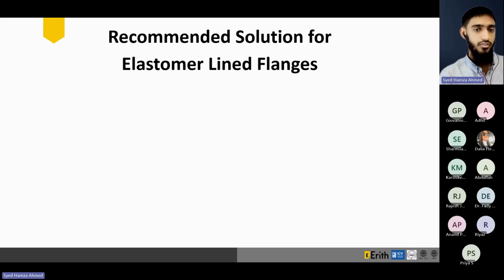Talking about elastomer lined flanges, we believe the best solution to this challenge is a thinner gasket, like a 1/32 inch or a 1/64 inch gasket made out of Gylon style 3522. The style 3522 material has very good permeation resistance, and when it is kept thin, it minimizes the amount of outward force that can be generated at the inner edges by the system pressure. Also, the style 3522 is pure PTFE, so it provides exceptional chemical resistance, and it will not stick to the rubber lining on the flange faces.